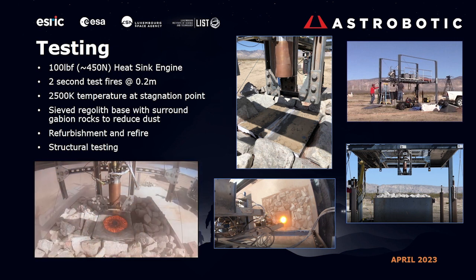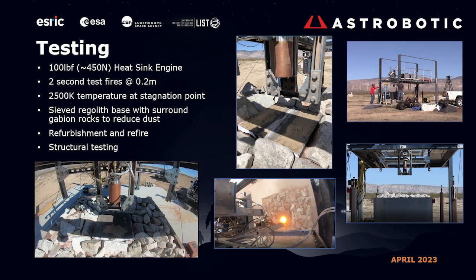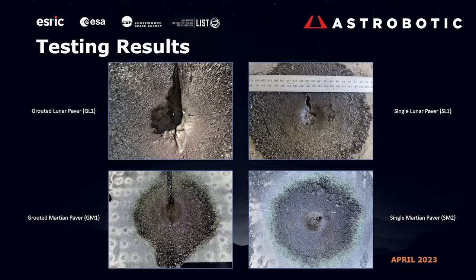The non-animated image that you can see in the middle, you can see that we fired directly onto the grouted surface. So for the testing results, they were extremely positive. This landing pad material was able to put up with the Methalox engine firing directly onto it, firing onto the bulk material as well as onto the grouted paths or the grouted channels that you can see right there. And those put up with things pretty well in either the lunar or the Martian curing versions that we had.